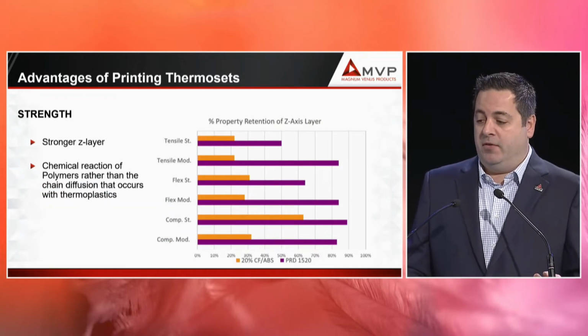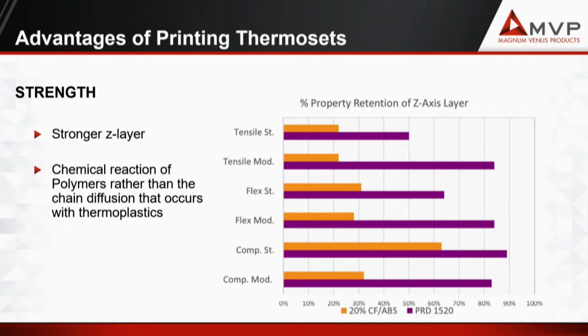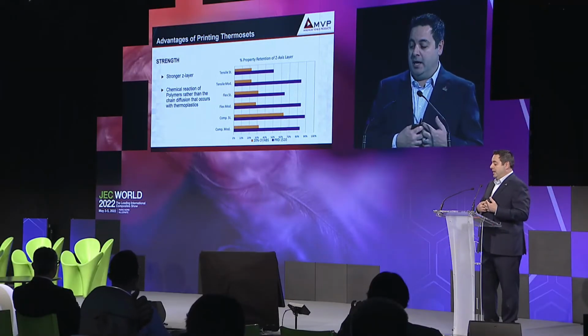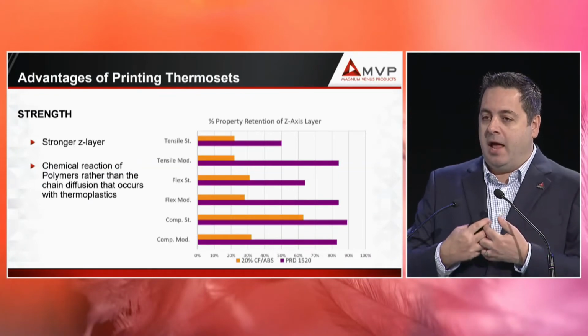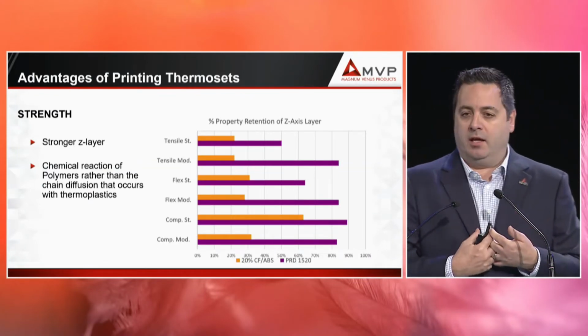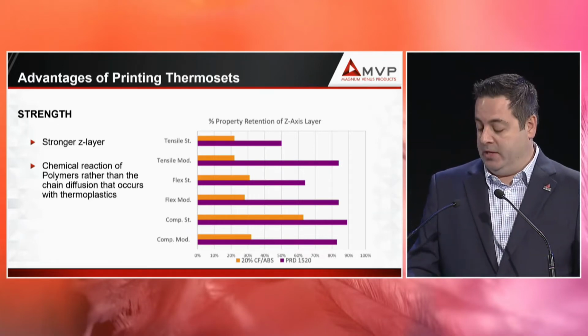One of the biggest advantages of using thermosets is a stronger Z-layer strength. The Z-layer meaning the bead-to-bead interaction. And again, this comes from a chemical reaction, not a thermal reaction. Some test data that has the orange here represents 20% CF/ABS versus a base material from Pollen, PRD. And you can see the tensile retention strength properties is much lower in the orange, the thermoplastic, than it is in the thermosets. It really comes down to that at this molecular level, you're entangling the fibers, you're entangling the different molecules.